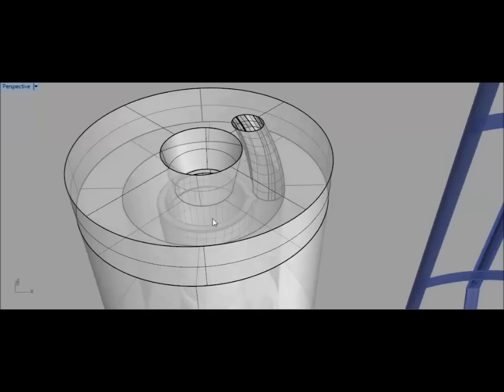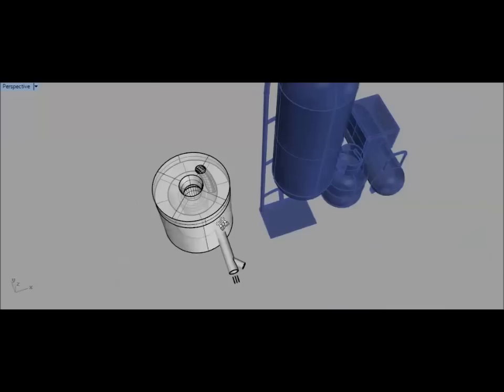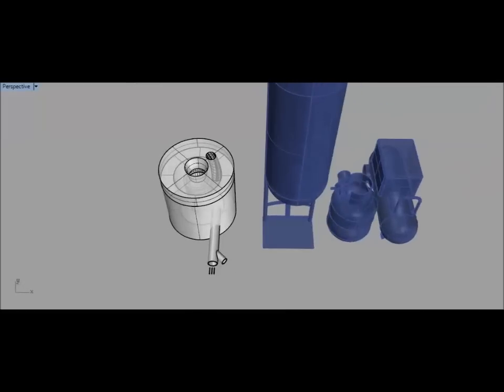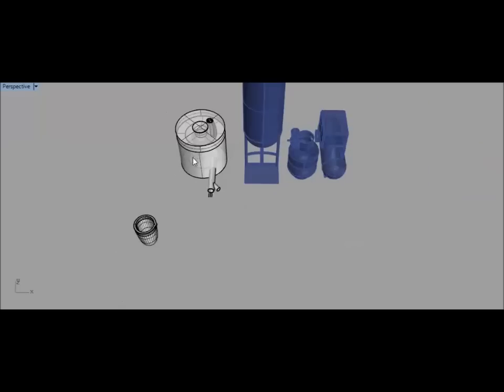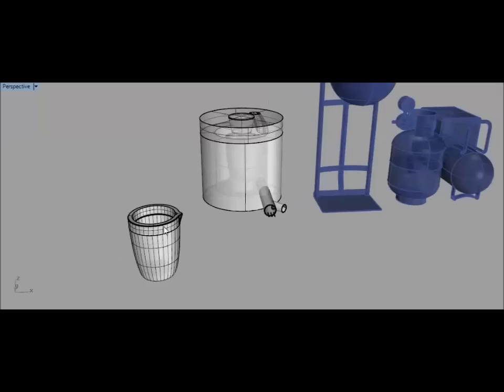And I also put the hole in the top, because I want to charge it. Now, one of the things I did is, I made this straight originally. And then as I started working through my workflow, I started working through the whole, how am I going to use this? I realised, I'm going to put that back in there, then I'm going to turn it off, I'm going to cool it down. Oh, dammit. If I cool this down and there are straight sides, it's going to shrink, grip onto that little plug, and I will not be able to get it out until it's decently hot again. So that conical shape means that if I place it on top, if it squeezes, it's going to push the plug up, not onto it. I'm hoping on that, by the way. It may still squeeze it, so we'll see. I'll do some shaving on the damn thing if I need to, with, I don't know, probably a file, actually. Probably a really rough file. Yes, so that's the basic design. And I thought, yep, I'm pretty happy with that.